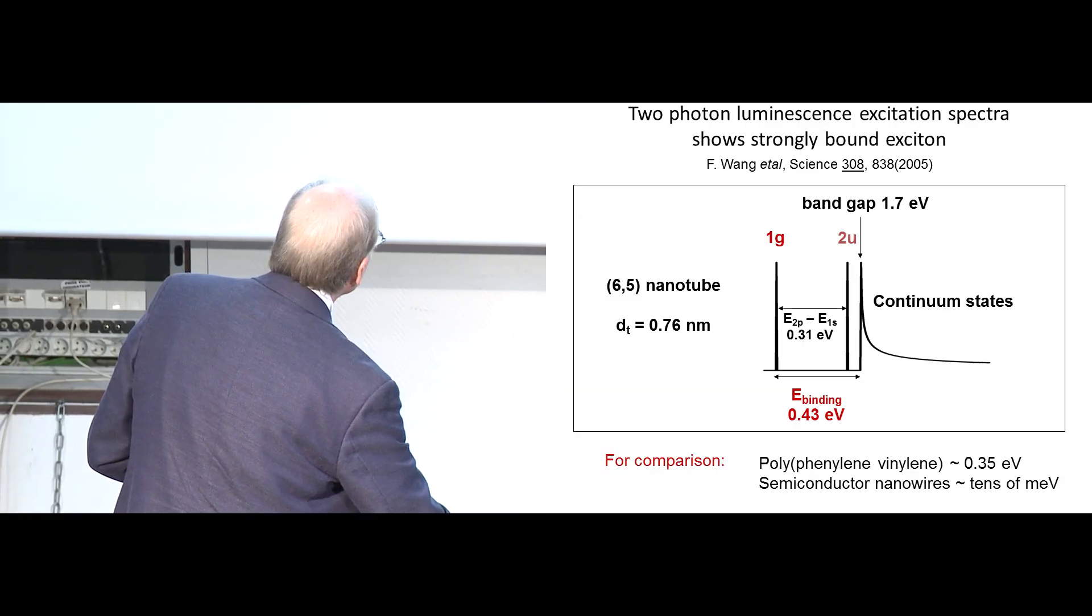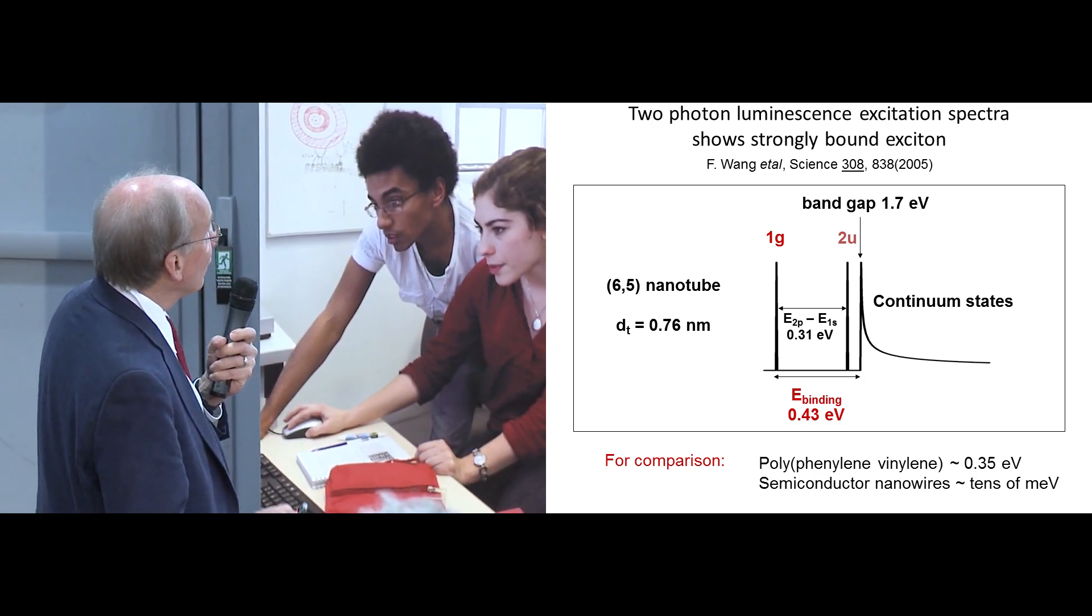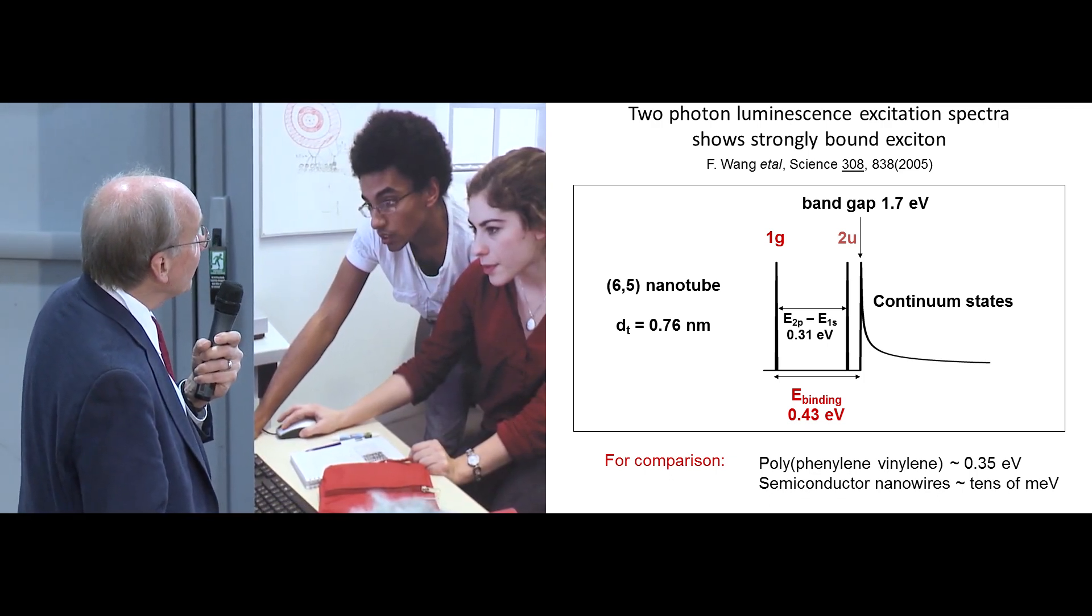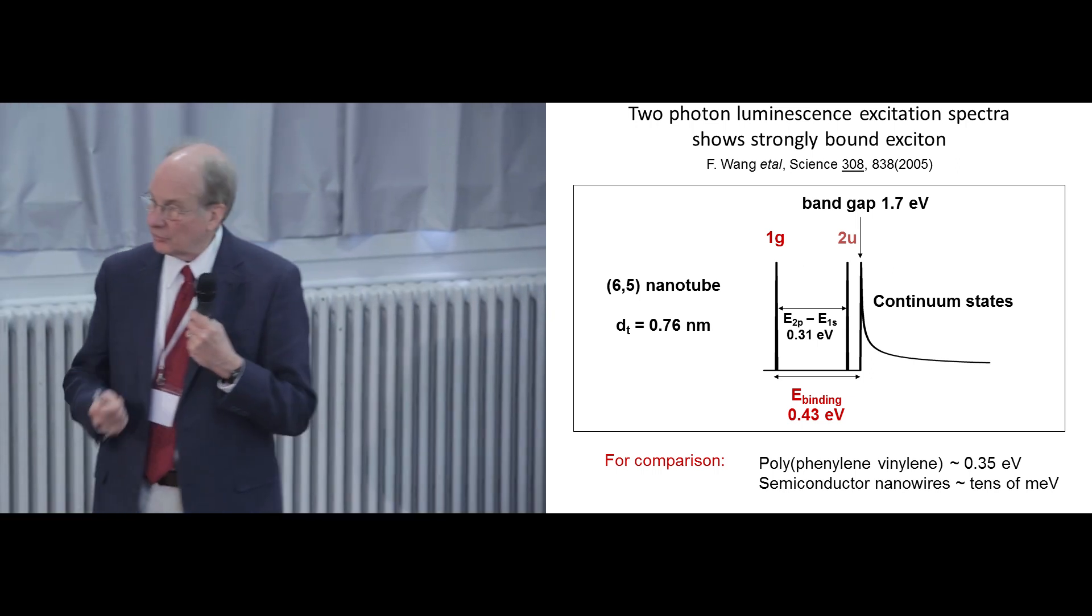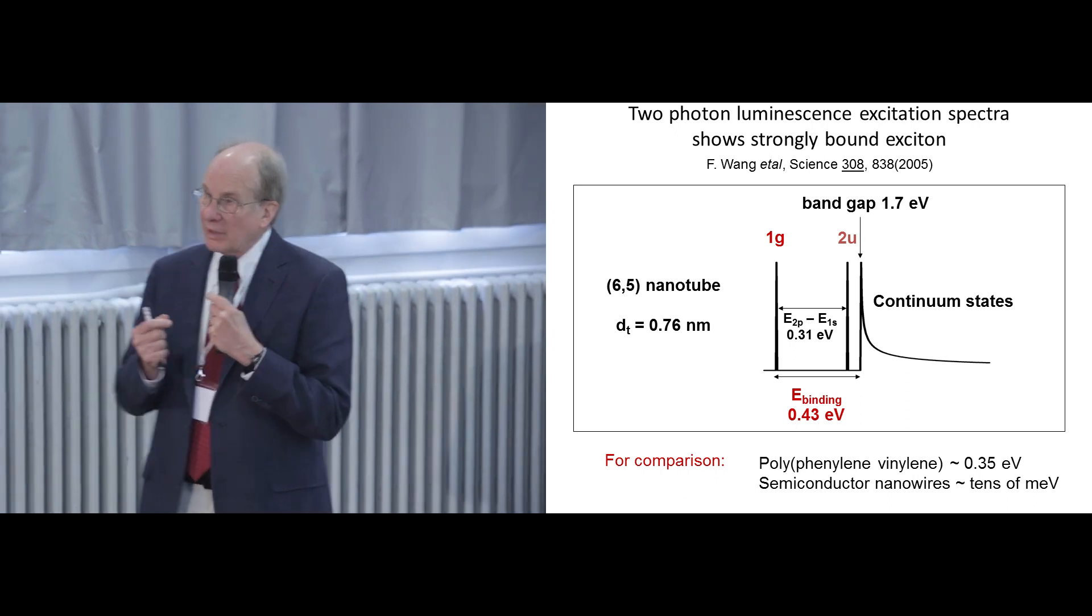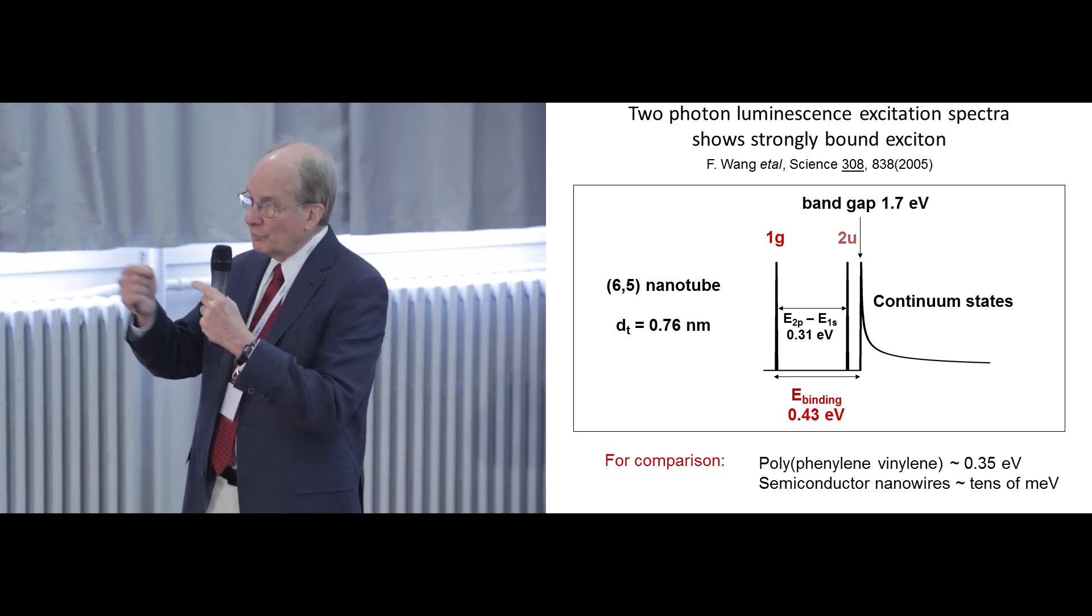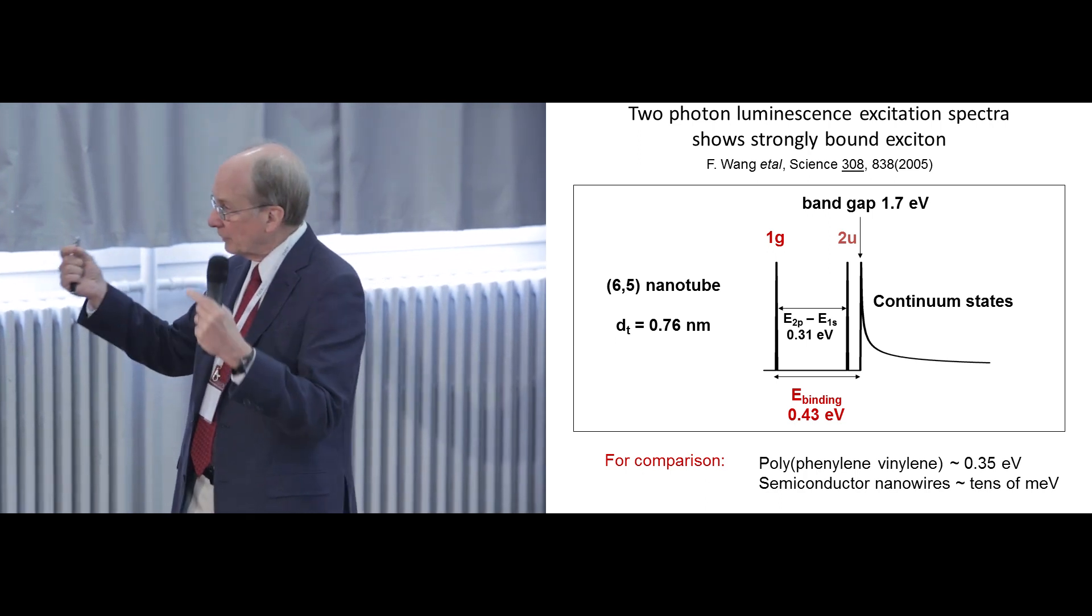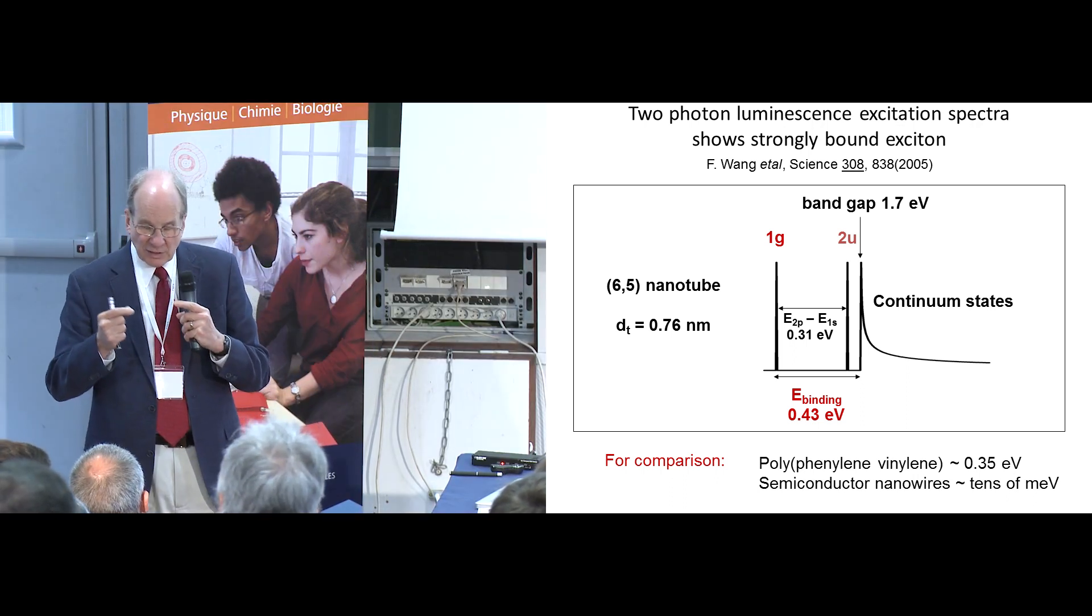With Gordana, who is here today, we measured the binding energy of the exciton below the band gap of the tube, and that turned out to be really strong. Four-tenths of a volt binding energy for the exciton. This is a true exciton as opposed to what exists in a nanoparticle. True exciton bound by the Coulomb interaction and able to dissociate into free carriers.